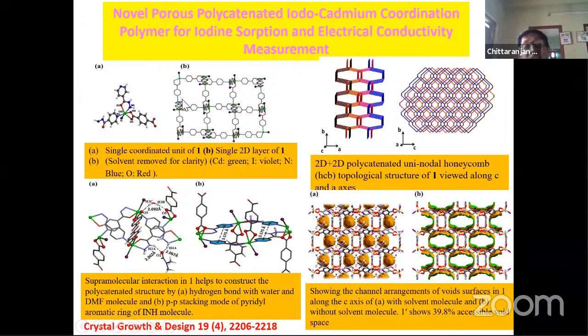Thus, it generates a coordination polymer, and that coordination polymer has a permanent cavity. That's why it is a metal organic framework. And this metal organic framework has this dimension. You can see the distance is around 4 angstrom, 3.575 angstrom. And there is around 39.8% accessible void space in the overall space. You see, the molecule contains some solvent. The solvent molecules are placed in the cavity.